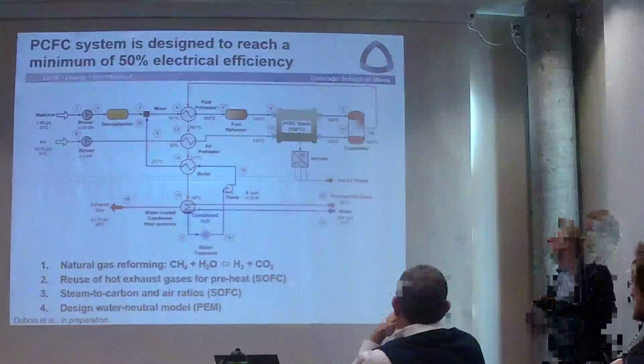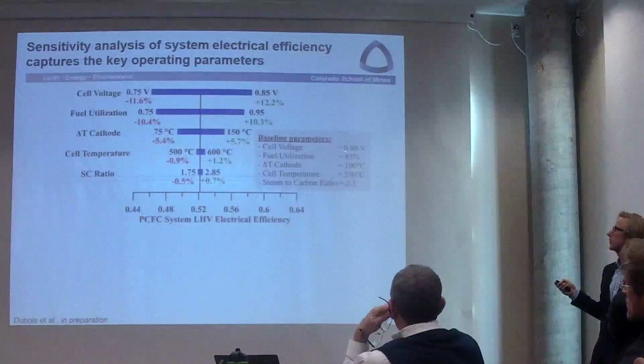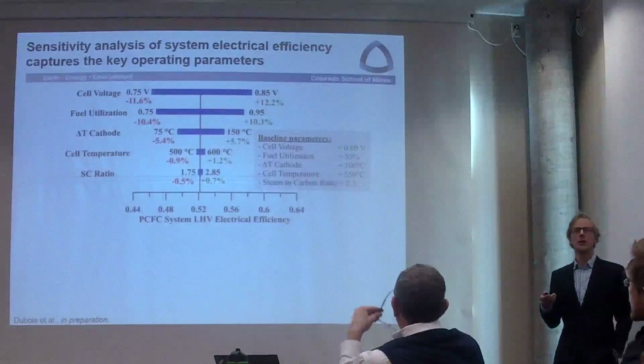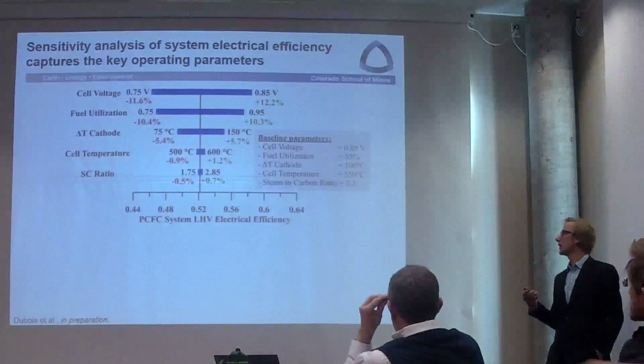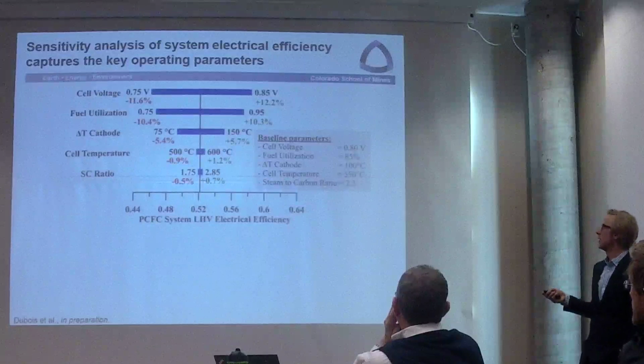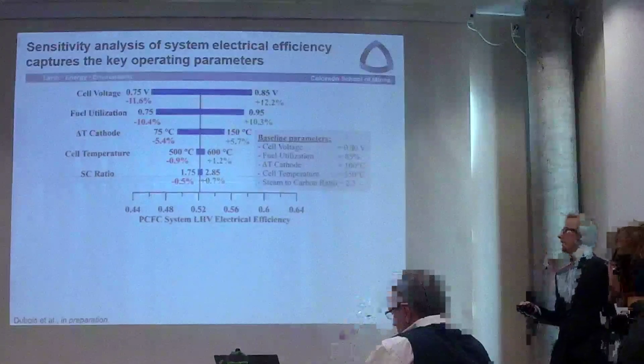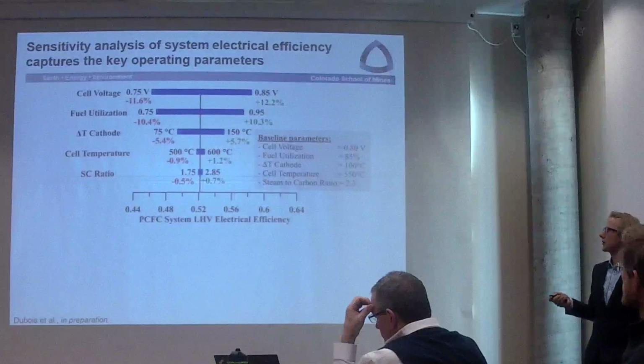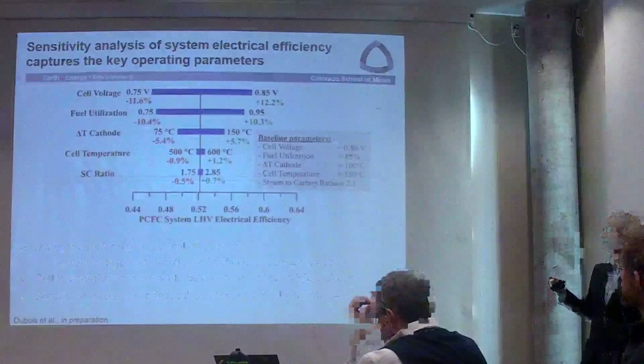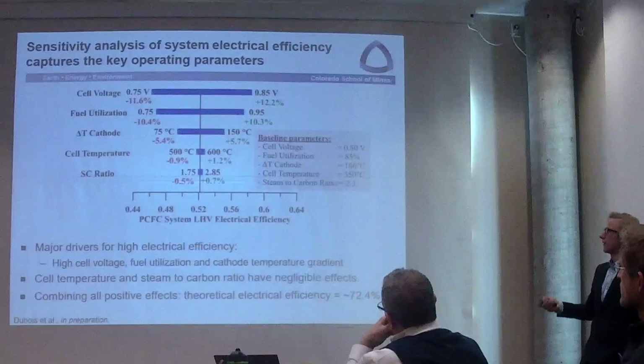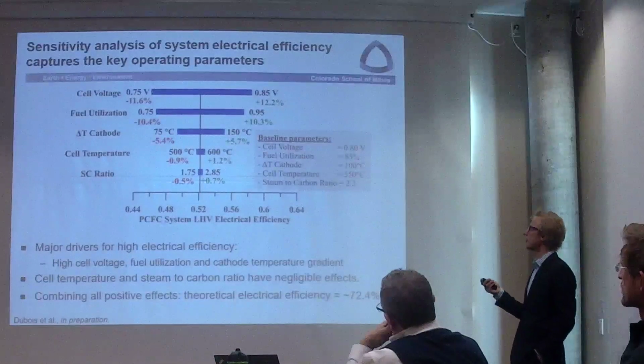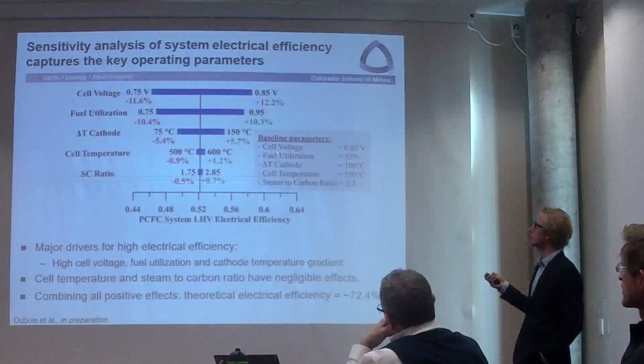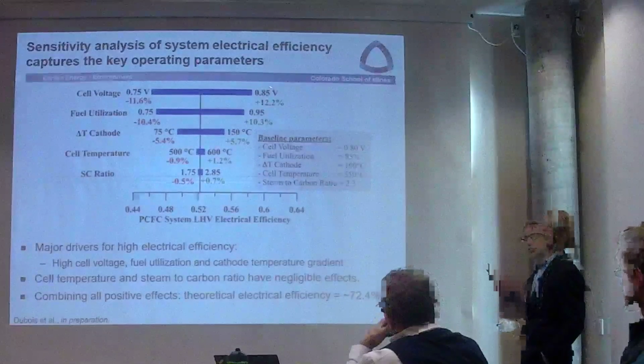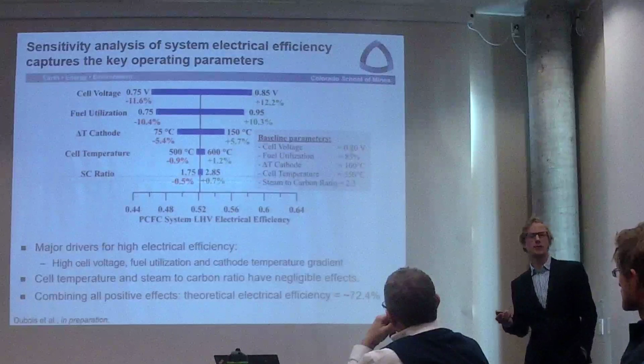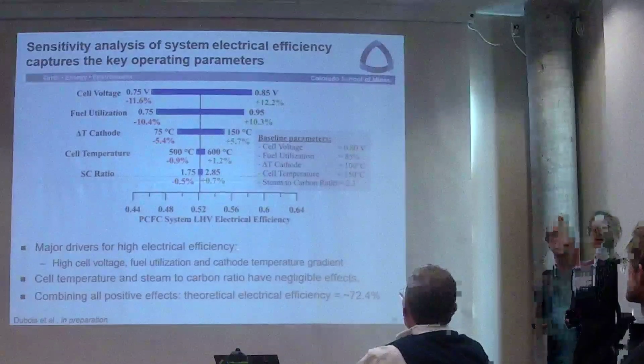Electrical efficiency: this is running at 0.8 volts, 85% utilization, with a channel to prevent any cracking and to prevent coking. Here we just start at a 2.3 steam to carbon ratio and then increase it, raising your electrical efficiency by almost 10 to 12%. Once you combine these, you get a value of about 72.4% electrical efficiency at this lower temperature of 550, still with performance of the cell and stack that is here.